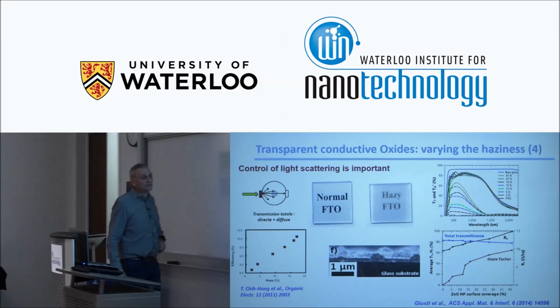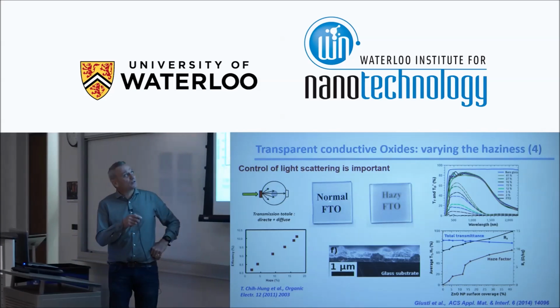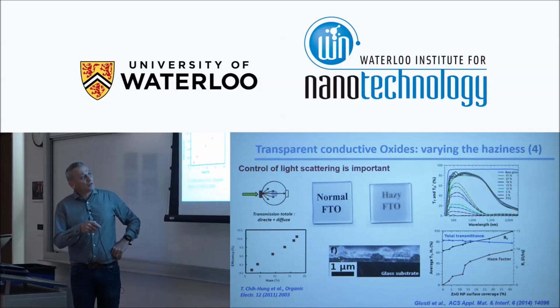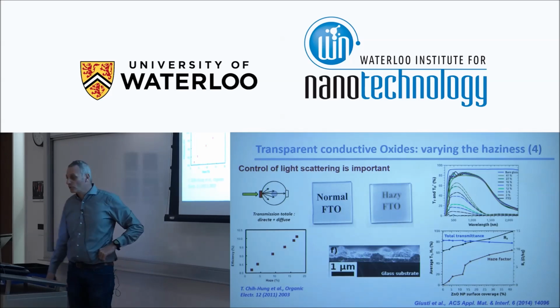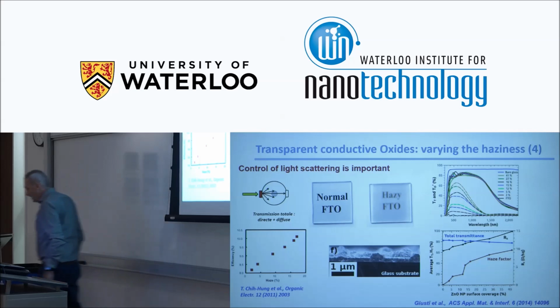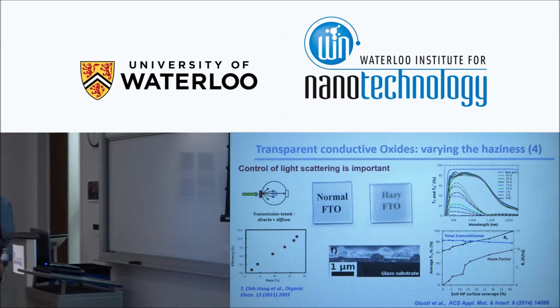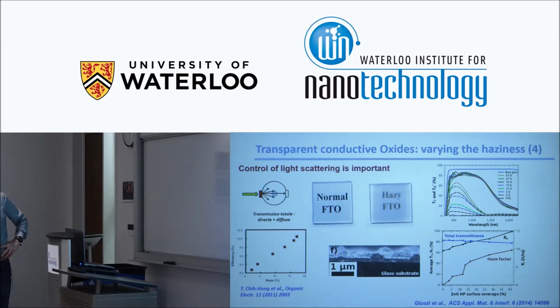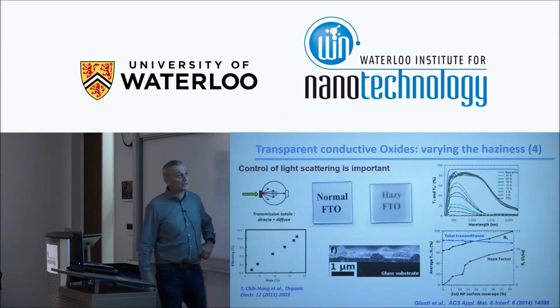And we found a way in the lab to have an FTO which is hazy like this. Just before depositing the FTO, we deposited some zinc oxide nanoparticles on a glass substrate. And depending on the surface coverage by the zinc oxide nanoparticles, we were able to vary the haziness. This is the transparency versus the wavelength for the bare glass, total transparency and the diffuse transparency. And depending on the surface coverage by the zinc oxide particles before depositing the FTO, we were able to vary the haze factor.